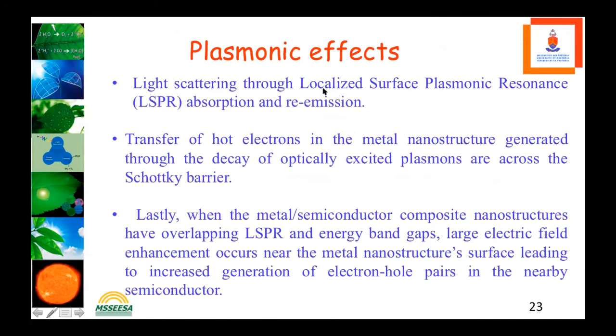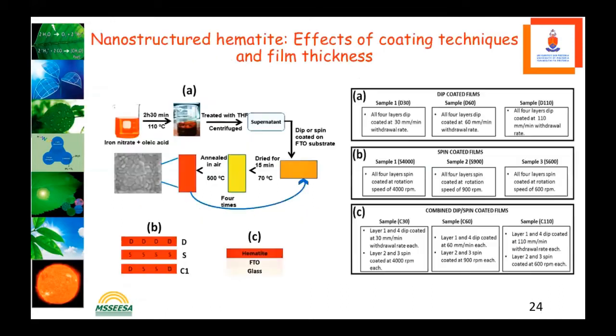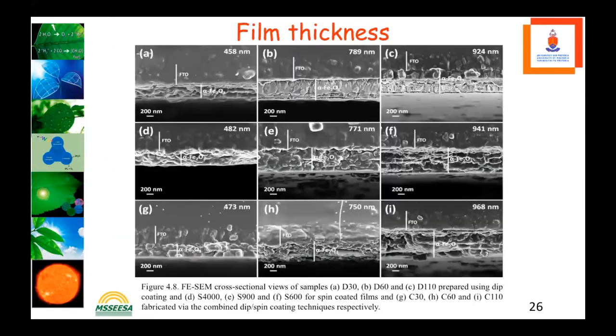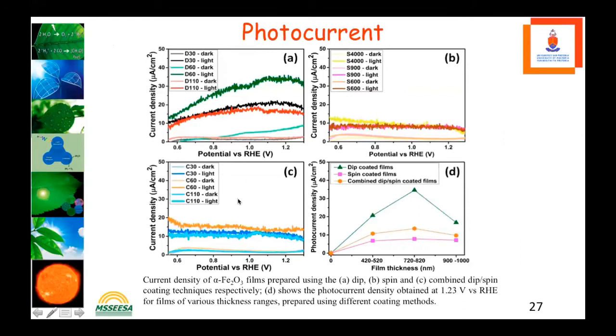Okay, the plasmonic effects: the metal inside any material helps with the scattering of light and improving the absorption and emission throughout the structure. So some of the results that we have found in our lab is that we have published a paper now where we have used the film thickness to see if we can find better photocurrent on this kind of work. And then let me just quickly run. The photocurrent improved as we shone the light on this material.